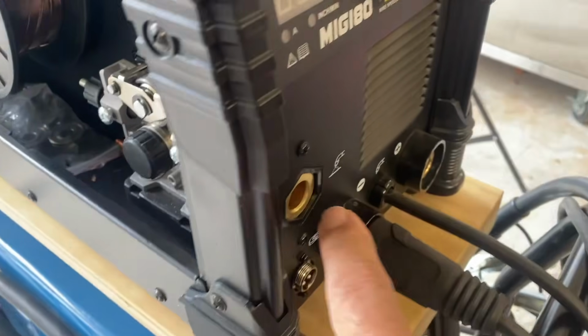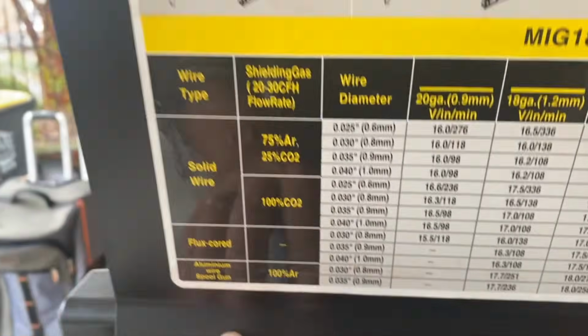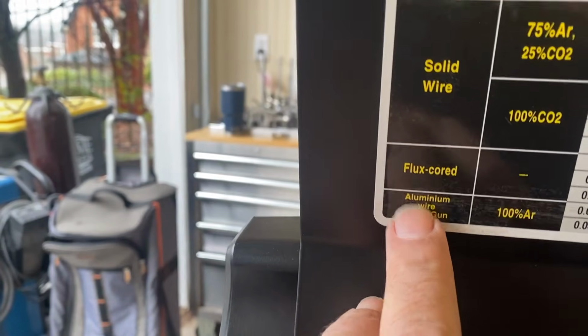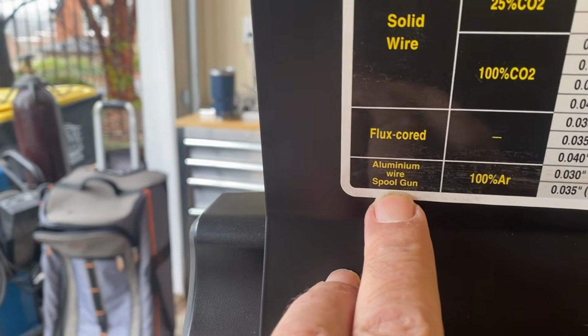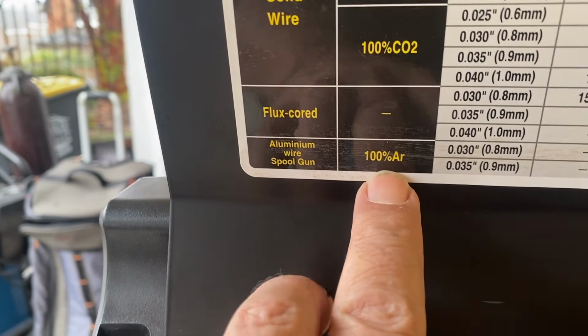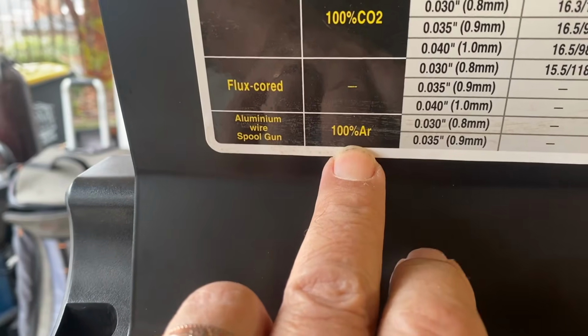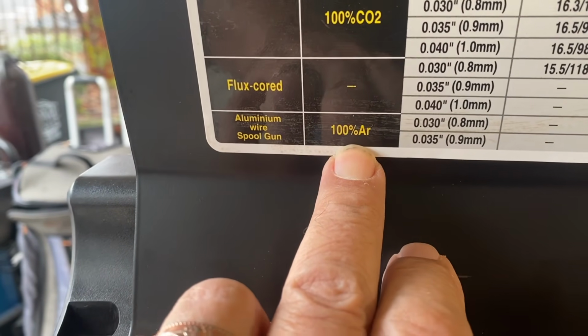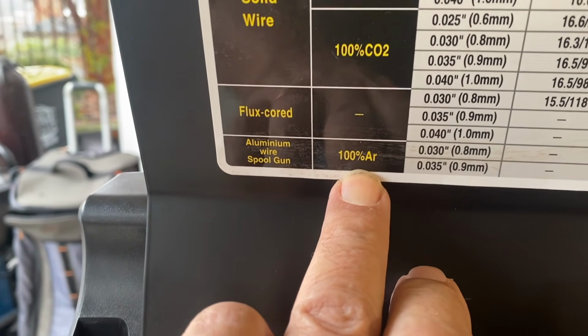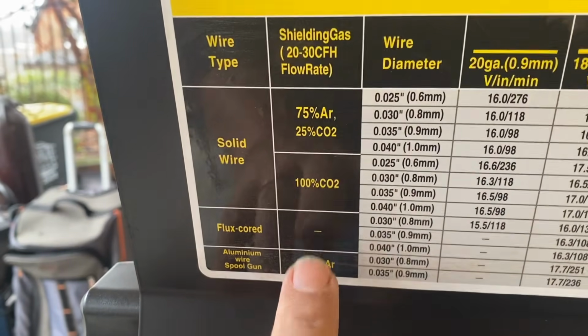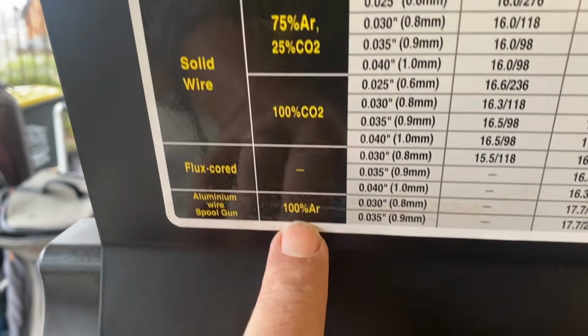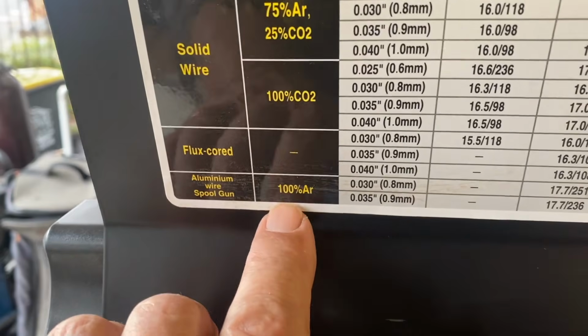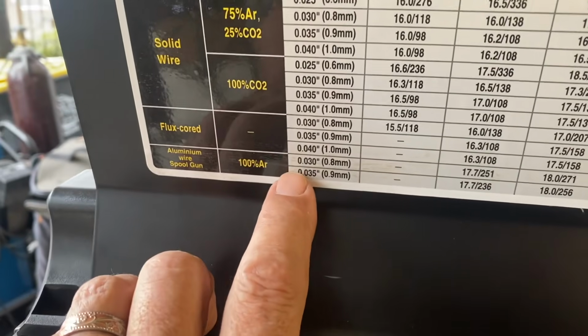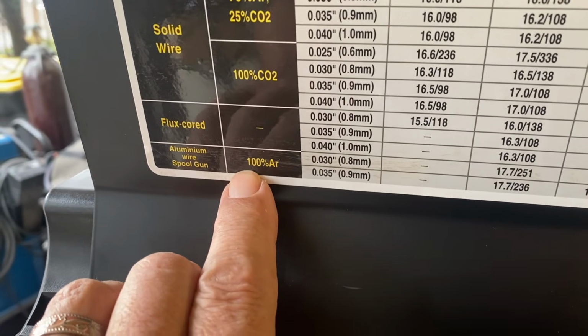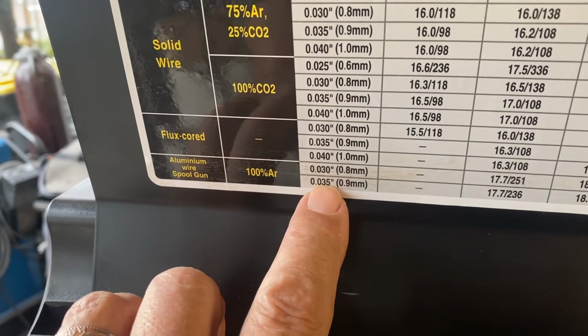Well, we're gonna hook the spool gun in here. Okay, look down here, aluminum wire spool gun, 100% argon. That is key. You can't do any good at all with your MIG gas for steel. Don't use 75-25, don't use CO2, strictly argon. There are a couple of other choices. You can use helium argon blends, Stargon AL, things like that, but 100% argon is the most common.